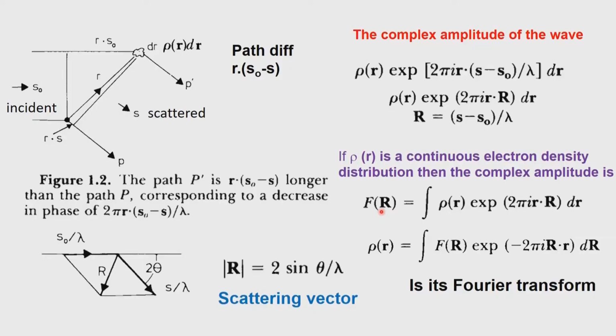So, we just saw that the two equations which are very crucial to our structure determination are these, the structure factor expression and the electron density expression. Now, we will see what relation comes from the geometry point of view, because the relation that comes from the electron density we now know: the more the electron density, the more is the scattering. Suppose you have a very big atom and a small atom, the contribution from the big atom is more to the scattering compared to that of a small atom.